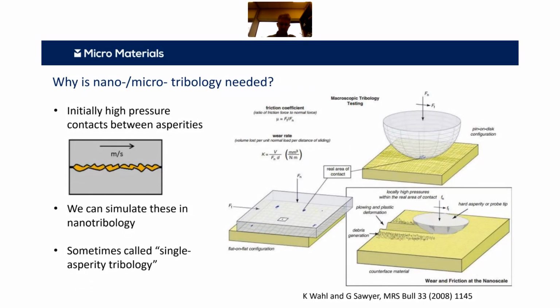But if you zoom right in, as there's this very nice example, somewhat famous paper here by K. Wahl and G. Sawyer, where they show that real area of contact is initially a tiny fraction of the actual area of contact. And there's been some very nice experiments done quite a long time ago now, where people have looked at transparent surfaces essentially, and the contact between sliding transparent surfaces as a function of load, and you can see just how much of the material is in true contact, and when it's not in contact, the light is scattered, so you have a very clear metric in terms of how much is in contact.